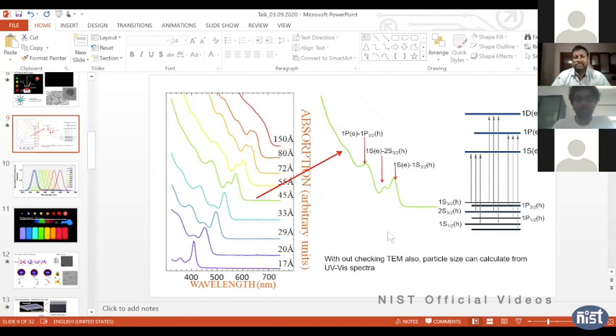Your absorbance is very broad. Like here you can see the 8 nanometer particle, the absorbance is not distinct, it's a broad absorbance. So that affects your absorbance. So when your particle is bad, not very good. So this is the initial way to distinguish your particle. After synthesis, whether it's good or bad, you can distinguish very well